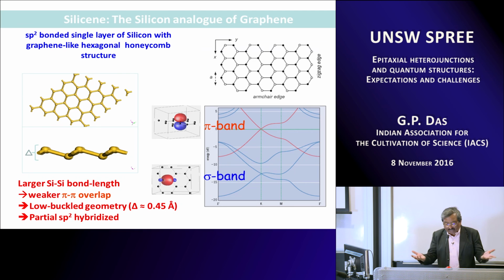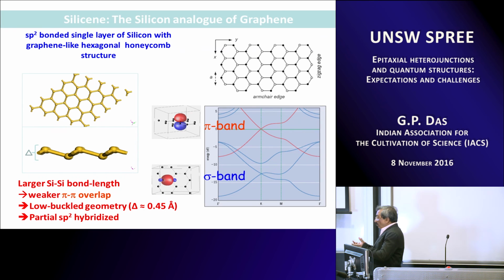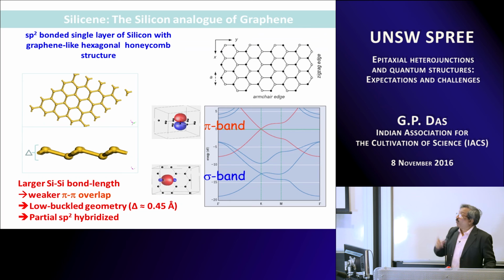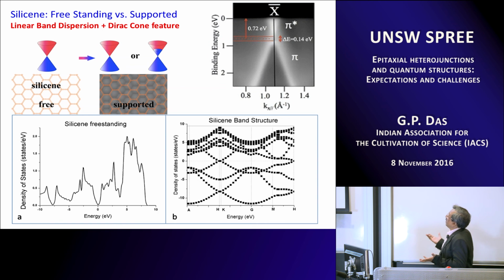And well, people have done its band structure for the freestanding as well as for silicene on different kinds of substrates. Now, my intention in this lecture is to tell you about what happens when you put silicene on a substrate, and what is the substrate induced phenomena that takes place. Well, these are all things which are from the literature. These are not my work. So you can see that silicene freestanding as well as supported, how the linear band dispersion and the Dirac cone, and this is the ARPES measurement which shows the apex of this cone, which is lying about 0.7 electron volt below the Fermi level. And these are the band structure and the density of states which are very well known for silicene today.